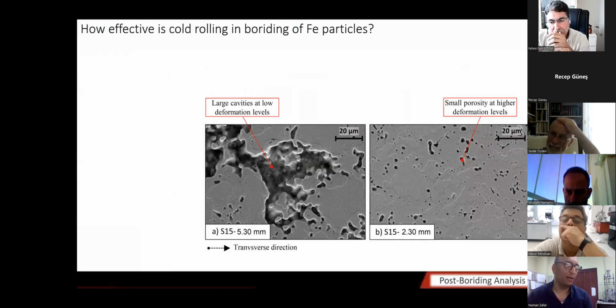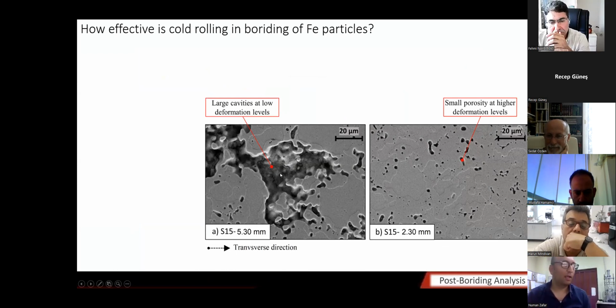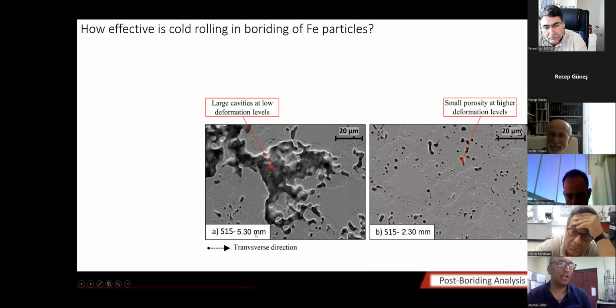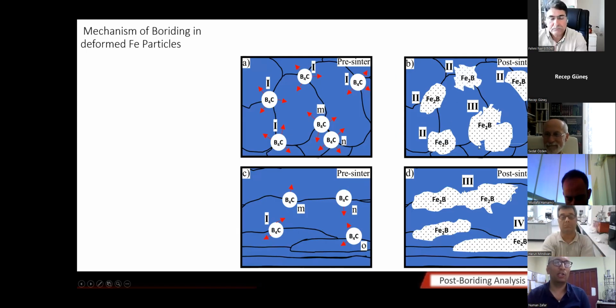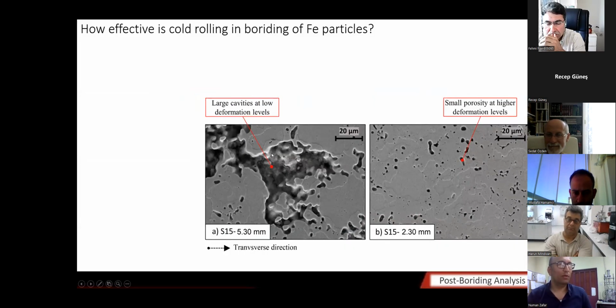What if I boride a material with no deformation and with agglomerated B4C particles? Well, this will happen: large cavities will occur in the core. And with the same material S15, if you deform it and bring it to a 2.3 millimeter wire, reduced porosity will occur. So agglomeration is not desired. This is also the reason we have used plastic deformation, cold rolling, to distribute the iron particles so that no agglomeration remains in the core. Eventually, a higher region is borided without agglomeration using cold rolling. And if you compact them without cold rolling, you might see these big porosities.